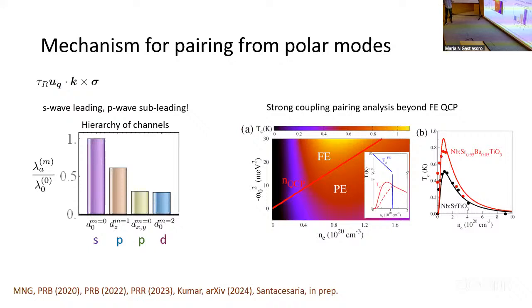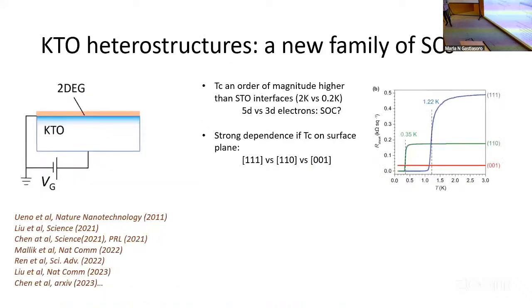There was some criticality that was unexpected, as in you get a peak of TC inside the ordered phase, which I don't think is very conventional, or at least it hasn't been pointed out in the other mechanisms, with magnetism and so on. Good, these two things.